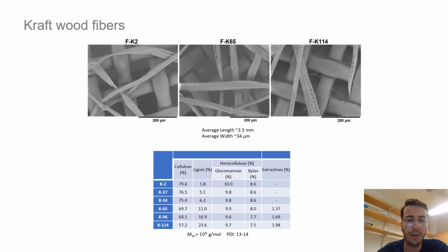You can see pulp fibers in these upper pictures. Fibers with kappa 2, you can see some parts of them are collapsed and we can see kinks and curvatures on them. But when it comes to kappa 65 and kappa 114 fibers, you can see they are straight and have less curvature and kinks. And here is the full chemical composition of the pulp fibers. You can see the pulp fibers with higher amount of lignin have lower amount of cellulose, but the hemicellulose content is quite the same for all pulp fibers, about 18 to 19%.